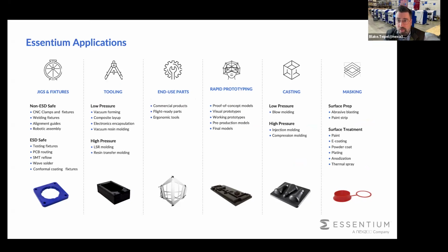and casting core boxes. So the large size of our systems, near 700 millimeters or so in X, these systems can produce a lot of the casting patterns and casting cores that are too large to fit on some of the other systems that are out there. So the build size can be a real advantage, especially in the areas of castings. And that's something that just last year, 2023, we saw a flurry of activity in the casting space. And so we're excited about that too.